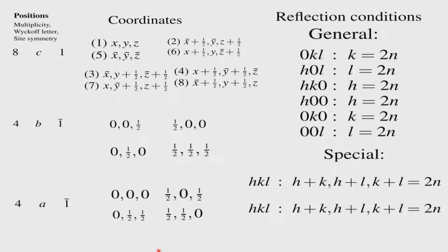The way the atoms are located, this is what we did in the case of zinc sulphide when we took that example in the earlier classes, and we found that it belongs to Pbca. If you want, you can go back to that example. You will see that the presence of the face centering in PBCA comes because the atoms are positioned in such a way that they mimic a face centered lattice.